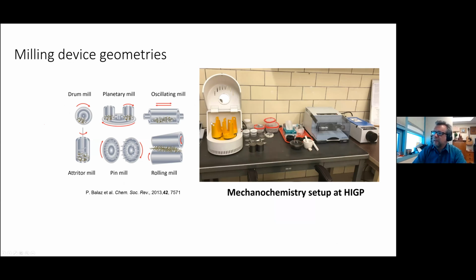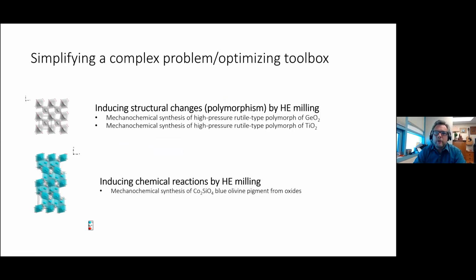One of them is a planetary mill, the other one is an oscillating mill, and examine whether we could try to induce some of these phase changes or chemical reactions that we are interested in by simply grinding samples at high energy. We decided to test this on a couple of simple systems. We chose two oxides, germanium dioxide and titanium dioxide, as testing systems for inducing polymorphic transformations. And we decided to try our luck at synthesizing olivine in a high energy mill by grinding together two oxides.